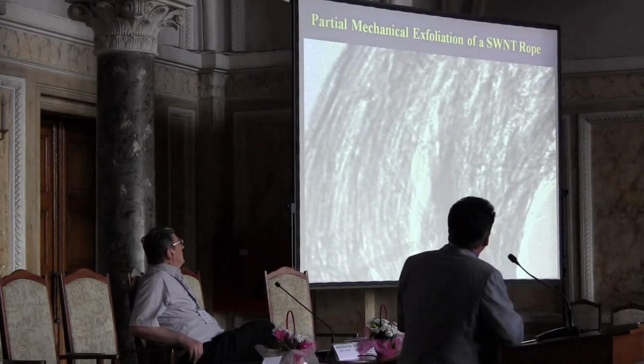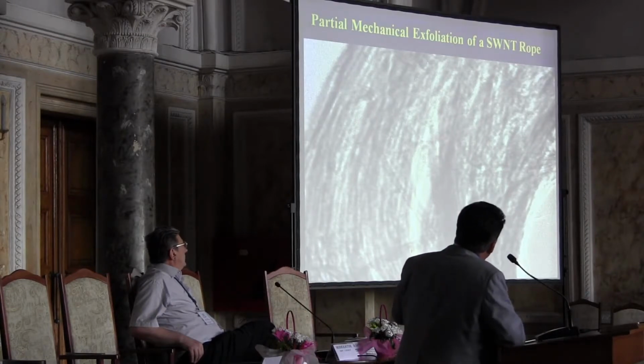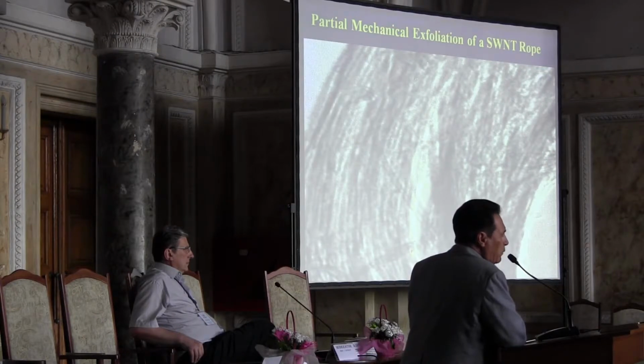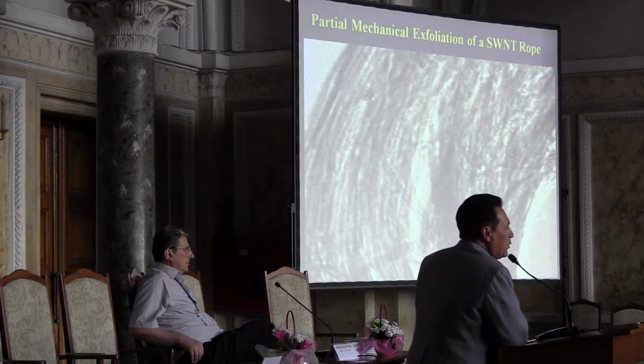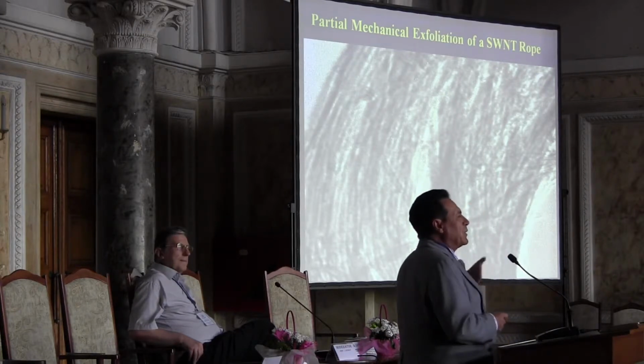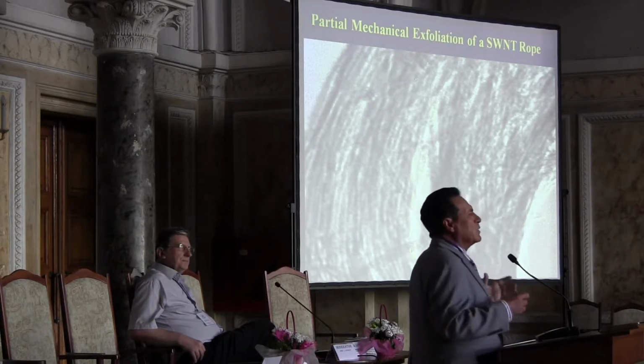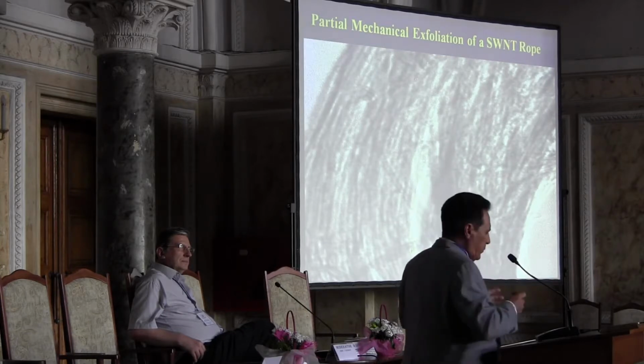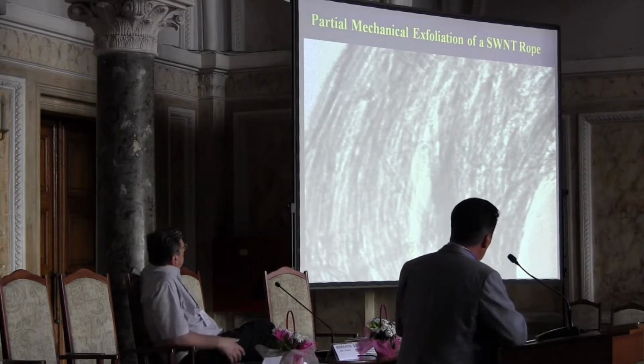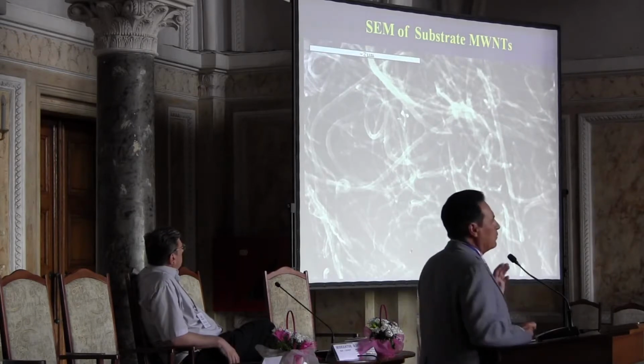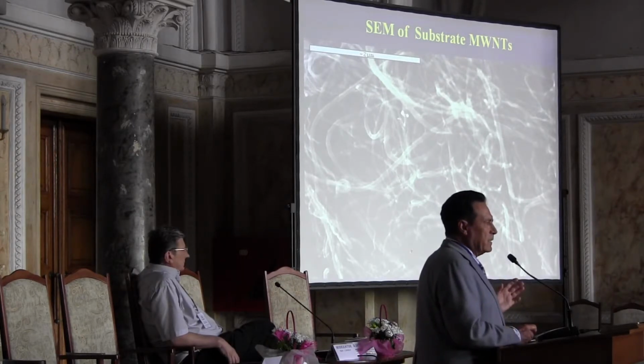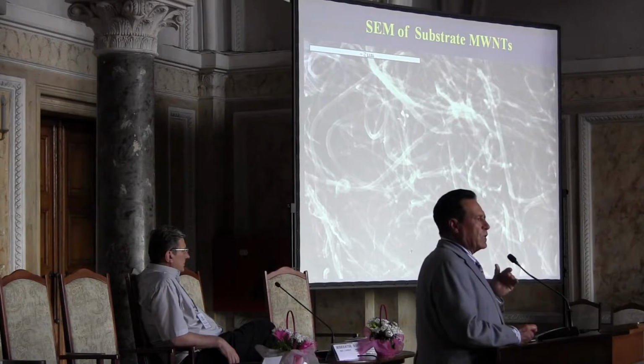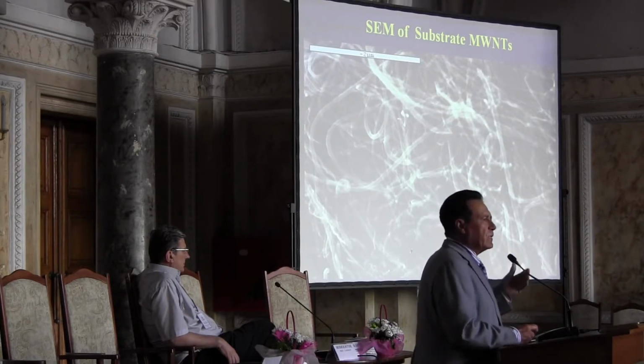Now, you can also do the exfoliation of these tubes by mechanical processes. So if you want to incorporate these materials, for instance, in nano zirconia, you can use a high energy planetary mill, when you mill these tubes with nano zirconia, separating them, exfoliating them. In the case of the multi-walls, it's easier, but the multi-walls, as we have seen, the properties are not so extensive.